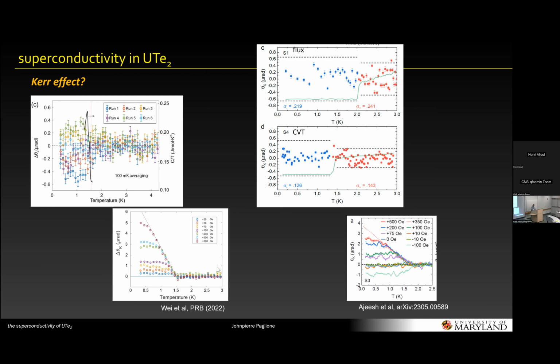Yeah. So the bottom two plots here are pretty much the same. I thought Los Alamos didn't see Kerr. So if you measure zero field cool, completely zero field, and measure Kerr effect, Aaron sees an envelope, which he claims is a signature of a Kerr effect at TC. Has he given up on that now, or does he still believe it? No, he still believes it. I see.